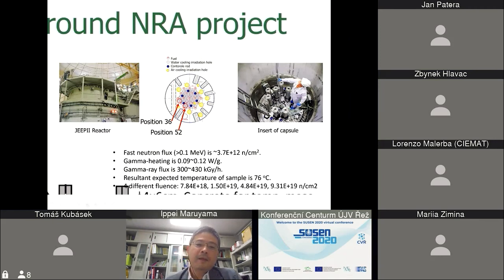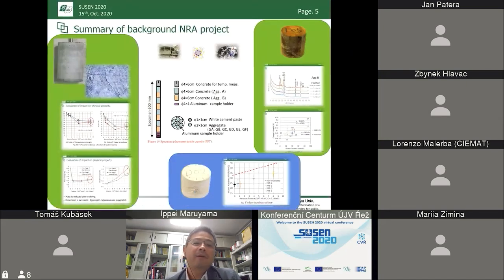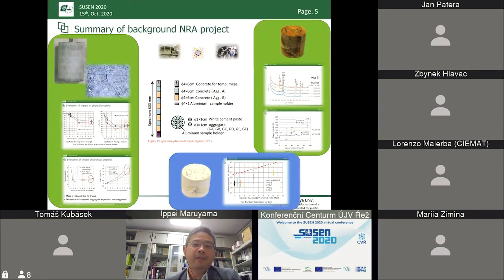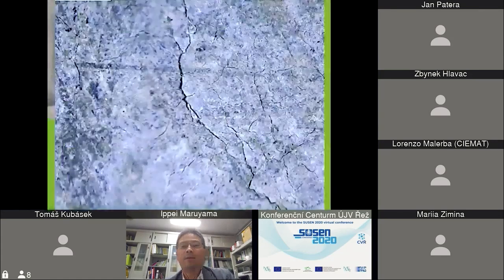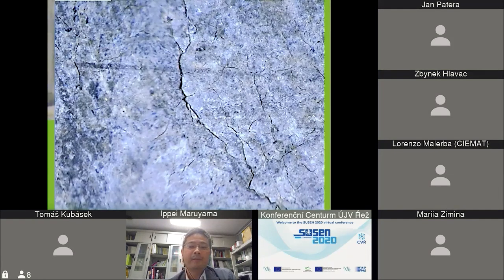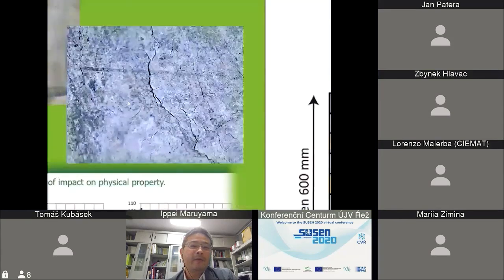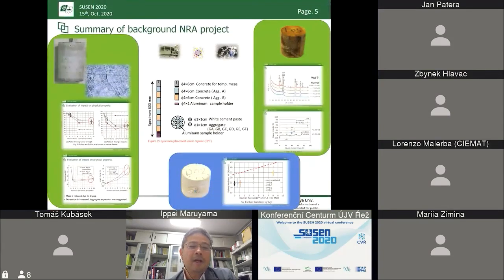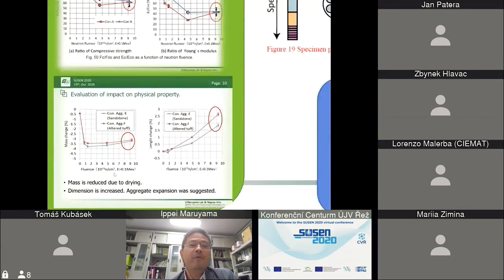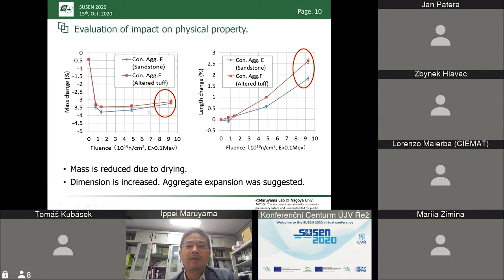And then after the irradiation, we found that the surface of the concrete showed a large amount of cracks. And then we found the reduction of mass and also an increase in the dimension of the concrete. In this figure, the x-axis is the neutron fluence, and the y-axis is the mass change and the length change. So you see the concrete was expanded on the order of 1% to 2%. This is quite huge.